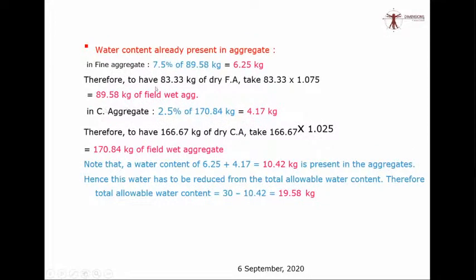I arrive at this because I have got 7.5%. So I divide 7.5 by 100, which is 0.075. I add it with number 1. So it is 1.075. I multiply this 1.075 with the initial value, 83.33. So if I had assumed 5% moisture in fine aggregate, I would have multiplied 83.33 by 1.05. If I have assumed 2.5 percent, I will multiply it by 1.025. I hope now you understood what I am trying to say.